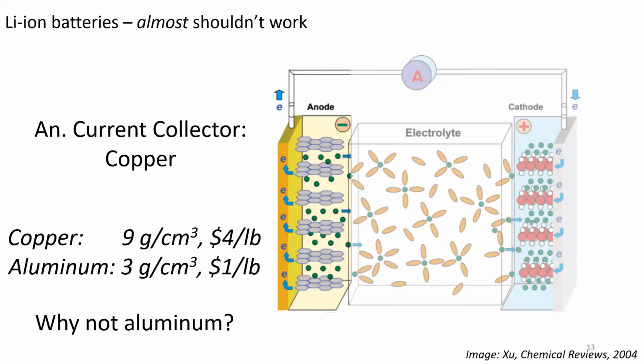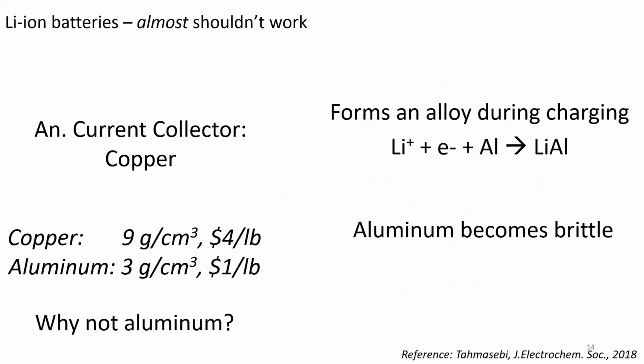Aluminum is less dense than copper, would make our battery lighter, and it's definitely cheaper. But we can't use aluminum as the anode current collector. And that's because aluminum and lithium like to form an alloy. They mix together, the way lots of different metals mix together to form alloys. And if we're forming an alloy at the current collector, and then deforming that alloy when we discharge the battery, and the lithium ions go to the other side, and then keep doing that cycle again and again and again, we're going to make that aluminum film really brittle, because we keep putting atoms in and taking them out, and it's not a layered structure like graphite.